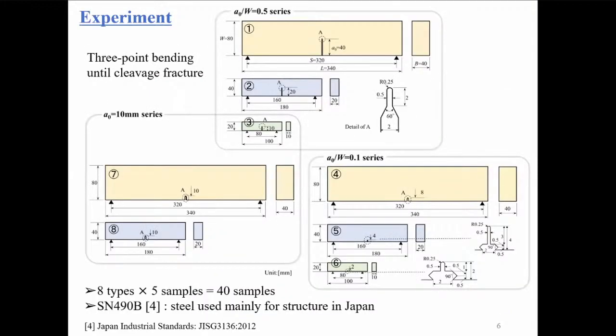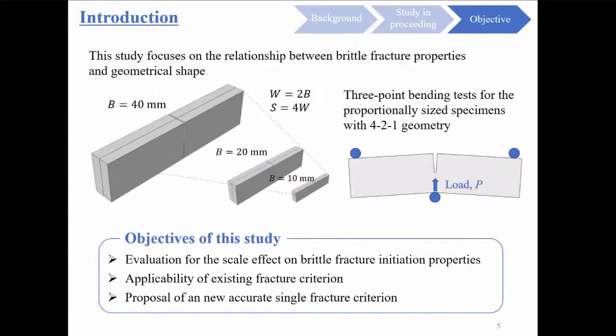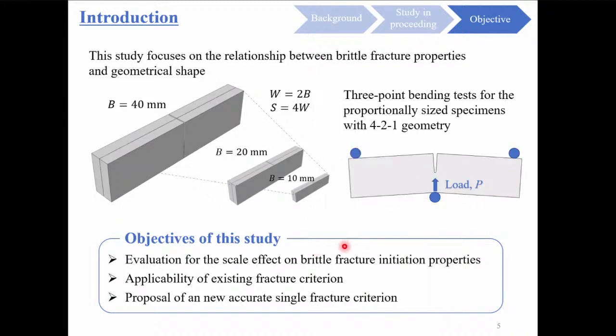I conducted 3-point bending tests on 8 types of specimens with different notch depths and specimen dimensions, but only the notch tip shape was the same. Based on the experimental results and finite element analysis, I evaluated the effect of specimen geometry on brittle fracture initiation properties, assessed the validity of existing fracture criteria, and proposed a new fracture criterion strategy.